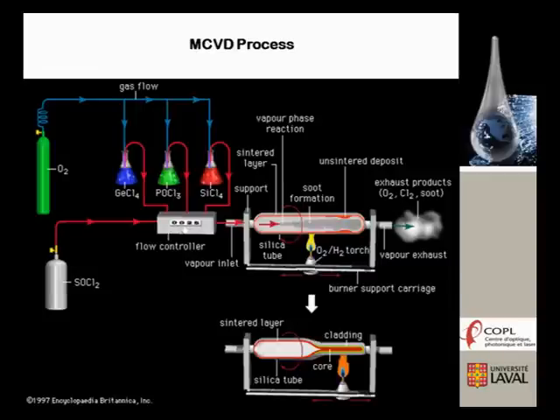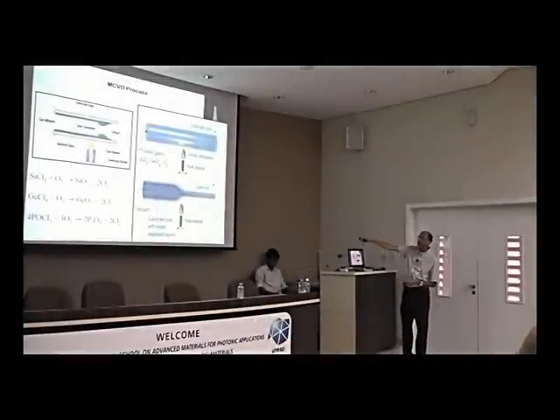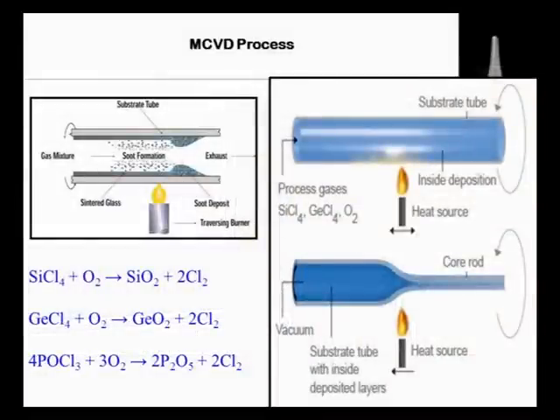Remember, we have decomposition here, at higher temperature, silicon chloride, and with oxygen, we have formation of particles, what we call nanoparticles of silica. If people speak about lots of nanoparticles of silica, we have them here in the glass at the end, and after that, we just make the consolidation process, and you get the cladding and the core of your preform. Of course, all the details of this process, all the details of the soot formation, all the substrate inside, you will have through this oxidation process. We have formation of silica, germanium, and phosphorus in the way to control the refractive index.